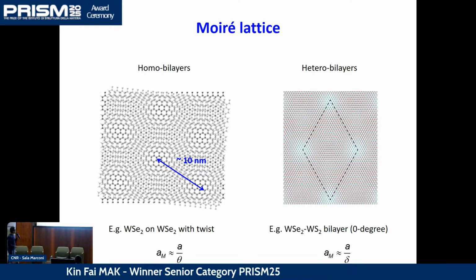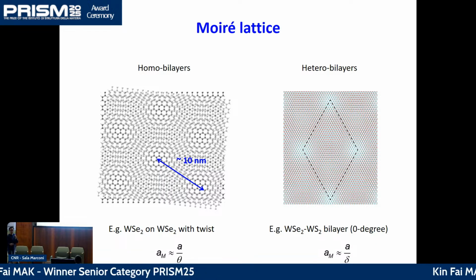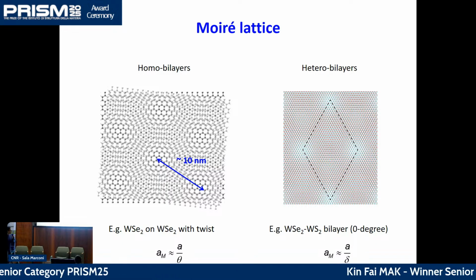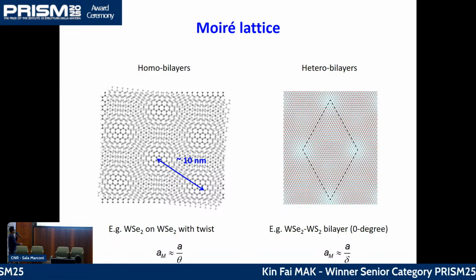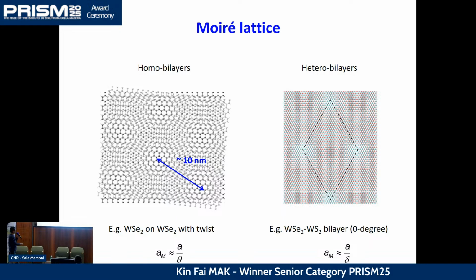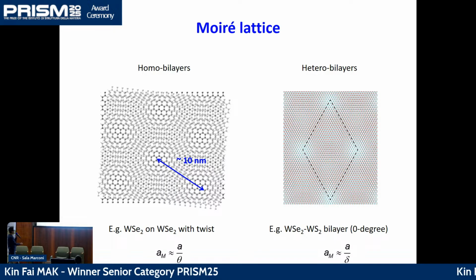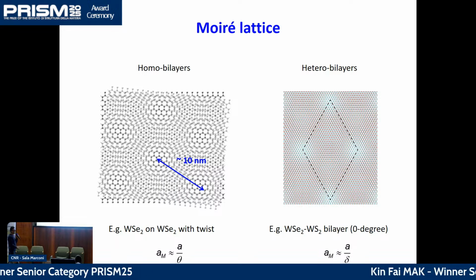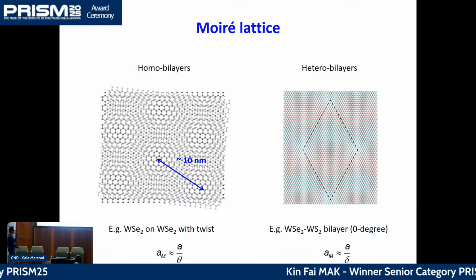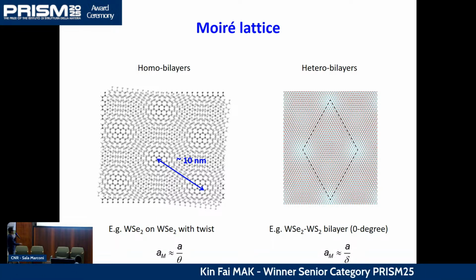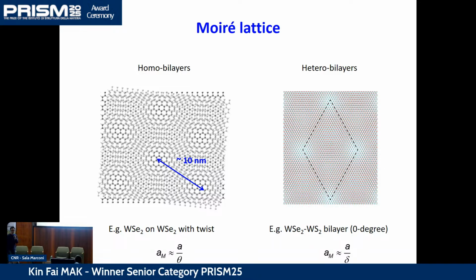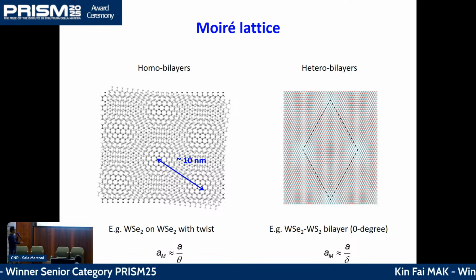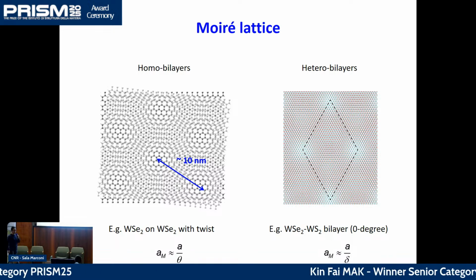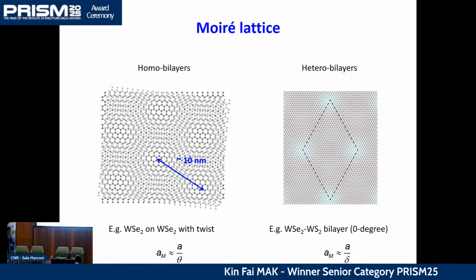Another way to create a moire pattern is to use two different materials, and you don't need a twist angle in this case. For instance, you angle align tungsten selenide with tungsten sulfide, and even with no twist angle, you still create a moire pattern. The reason is the lattice mismatch between the two materials. In this case, the moire period is given by A divided by delta, where delta is the lattice mismatch. Delta is about 4% in this combination, and that will give rise to a moire period also on the order of 10 nanometers.